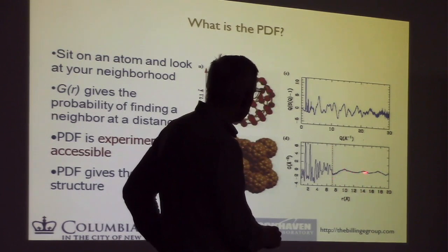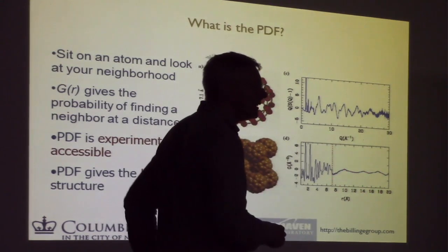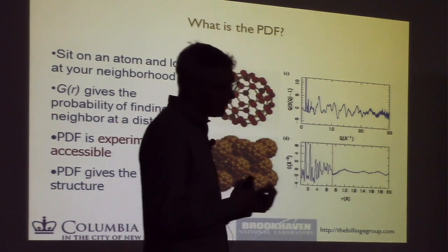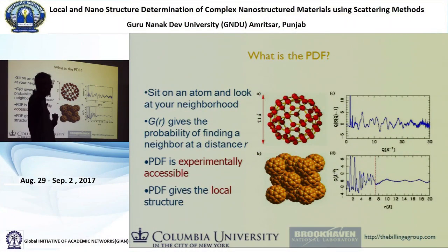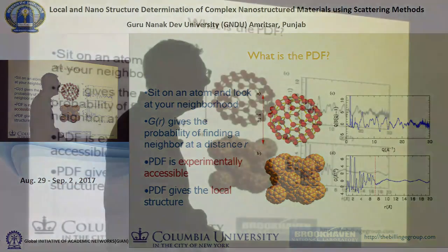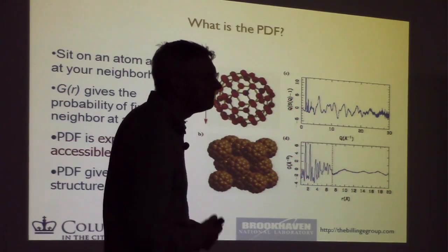Now, these peaks come from the arrangement of the balls. So what you're doing with the pair distribution function, you're always sitting on one atom and looking at your neighboring atoms or your other atoms. So for these guys, we're sitting on an atom on this ball, and we're looking at an atom on that ball. But because of this dynamic reorientation, all of that atomic density is smeared out. So you just get a very broad peak like that. But it's peaked at the ball-ball separation distance. So these balls are 10 angstroms apart. That's why that's 10. And this is FCC, so the second neighbor distance is root 2 times 10, and the third neighbor distance is root 3 times 10. So 14 and 17. Does it make sense?